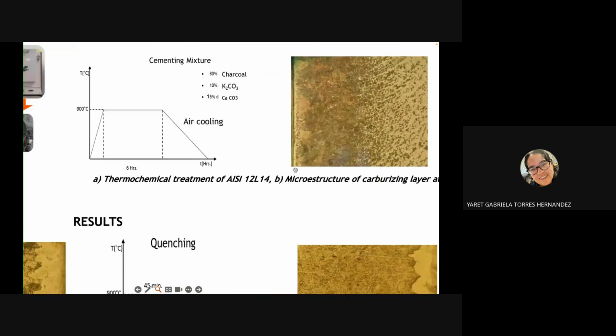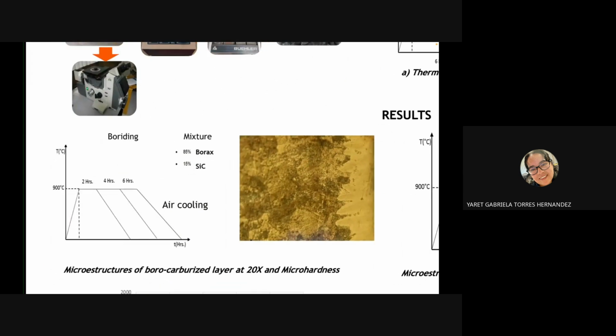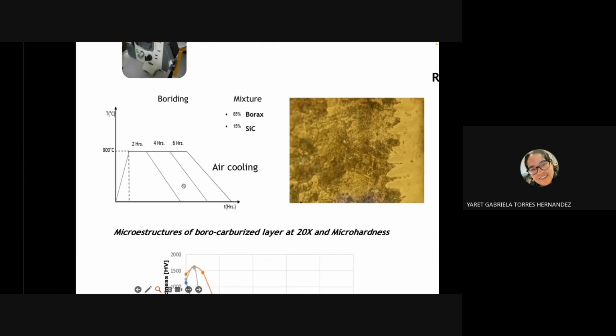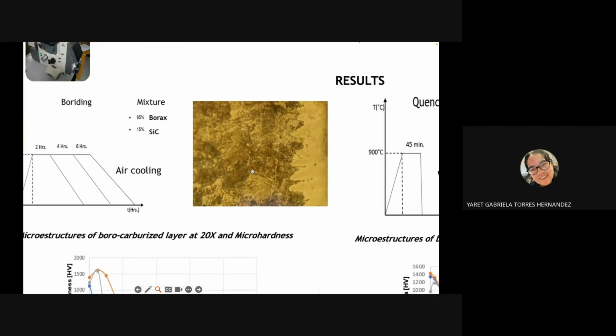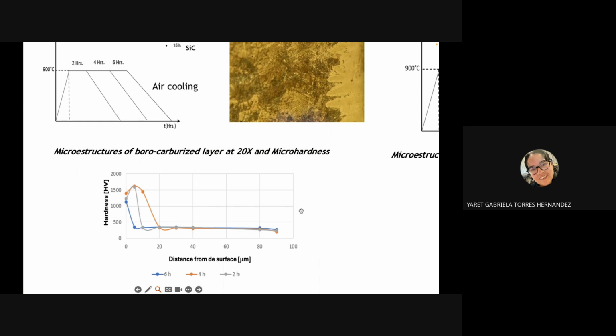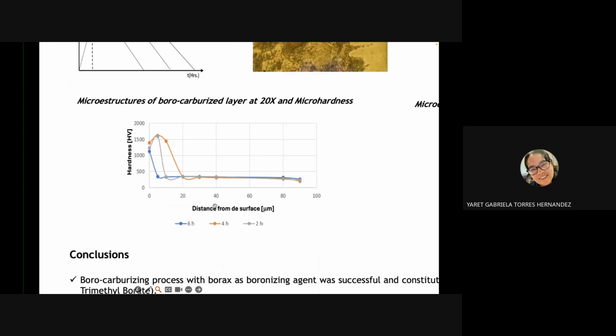followed by a boriding process during 2, 4, and 6 hours with a boriding mixture with 85% borax and 15% silicon carbide, and air cooling. The micrograph of a transversal section of 12L14 steel with boriding shows a sound morphology of the boride layer. For the sample at 4 hours, the layer depth was 40 microns and the microhardness was 1,400 HV of the borocarburized layer.